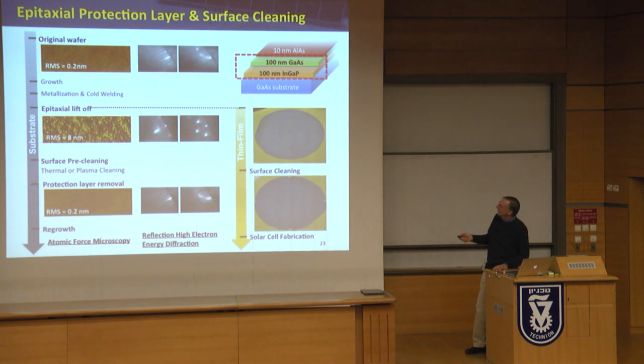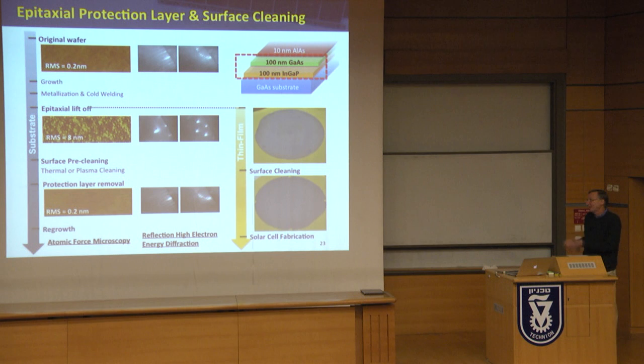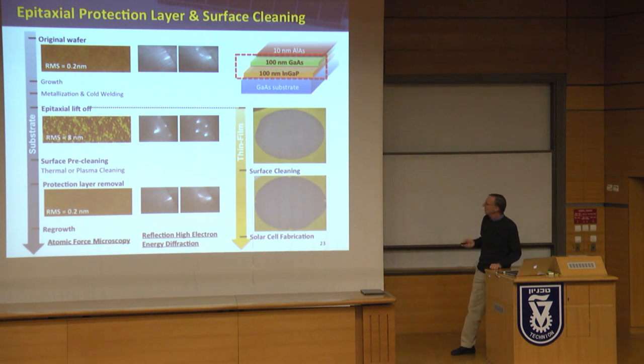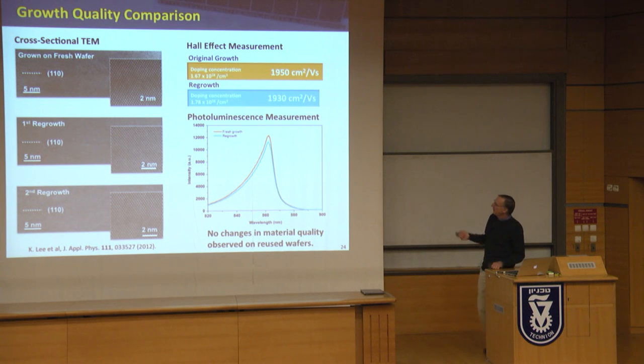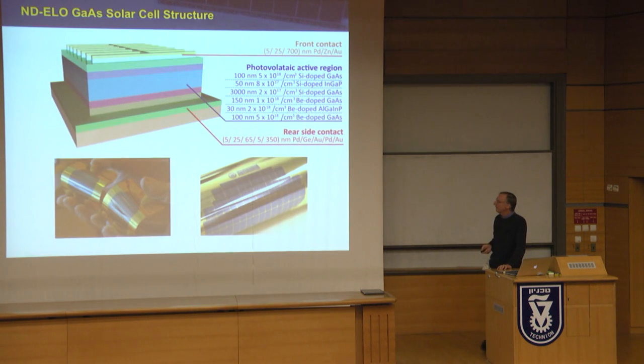So just some more stuff to show that the RHEED pattern of the original and the RHEED pattern of the processed wafer is identical. If you didn't do it our way, you'd have to polish it, and that polish takes off 10 microns, so you really don't have many cycles left. And you can keep doing it. This just shows the interfaces, the regrowth interfaces, second regrowth, first regrowth, and so on. I'm just trying to show you that we really do return back to the original wafer.